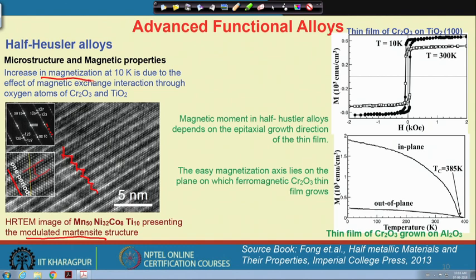The increase in the magnetization around 10 K, due to the effect of magnetic exchange interaction through oxygen atoms like chromia and titania, is shown here. This is a thin film grown on a titania 100 direction, and the film is made of chromia. From 300 K to 10 K you can see there is an increase of the magnetic exchange interaction and magnetization. So, the magnetic moment in a half Heusler alloy depends on the epitaxial growth direction of the thin film. People have observed very similar behavior when they grew chromia on an alumina substrate.